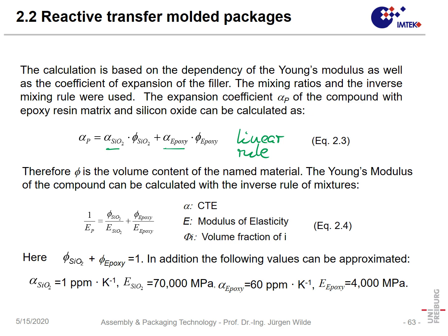When we look at the Young's modulus, for instance, we can say we have an inverse rule of mixtures. The inverse of the Young's modulus of that molding compound, or plastic as we say here, would be, again, let's say that's a molding compound, the portion of silicon oxide divided by the Young's modulus of the silicon oxide plus the portion of the epoxy divided by the Young's modulus. So that here is the volume portion.